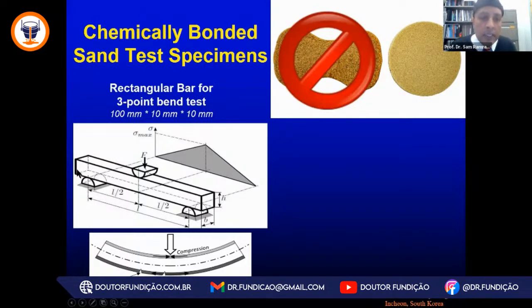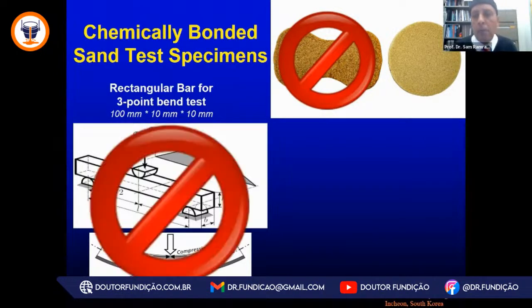We have found that the Kit Kat bar, I'm keeping everything like food today, this rectangular specimen, is an excellent type of specimen to get, again, mechanical properties. The shear, the modulus, the ultimate strengths and compression and tension are well understood in 3-point loading of the Kit Kat bar specimen, this rectangular bar. But again, with this specimen, we only get mechanical properties. And for that reason, we have modified the shape of the specimen to this cookie shape, because shape is a factor in casting. If you have complex geometry, we don't always understand the thermomechanics, and even the pure mechanics or the pure thermodynamics, much less the thermophysical and thermochemical changes that could be caused. So shape is a factor.